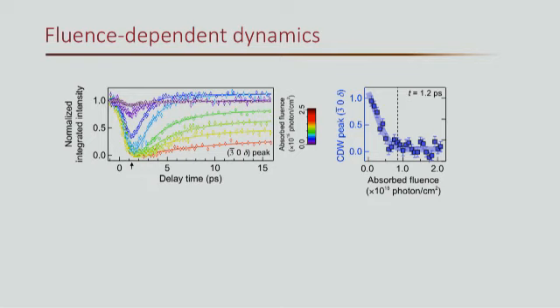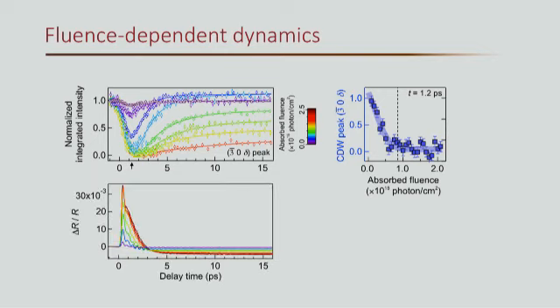Basically, reflectivity reflects how the dielectric constants change as a function of time as you populate different bands and excite quasi-particles to cross the gap. So when we do that, this is what we get. Different curves correspond to different excitation fluence. We tune the pump power, and each trace represents the change of the reflectivity normalized to its normal reflectivity before the arrival of the pump pulse. So again, there are several features in this plot.